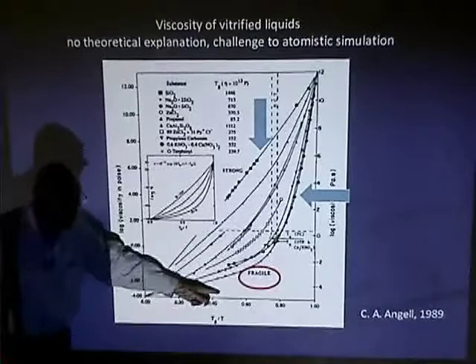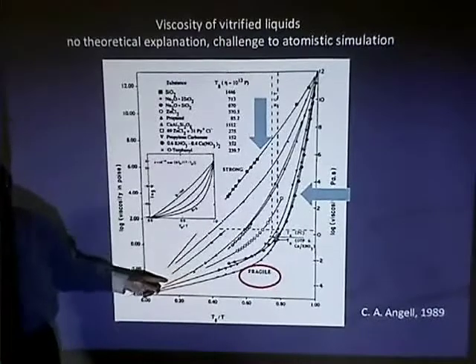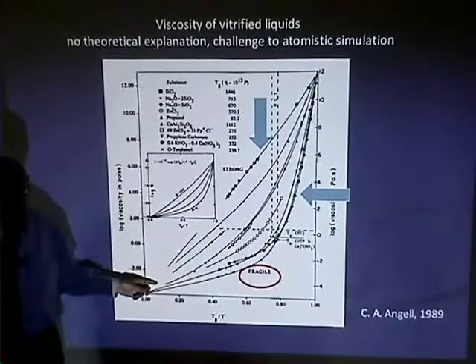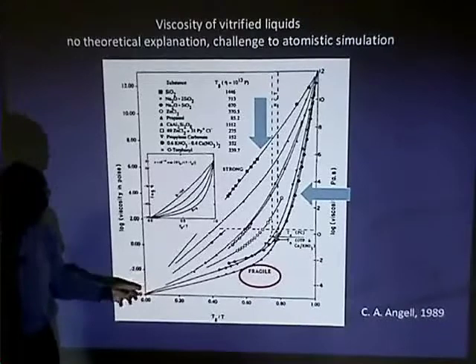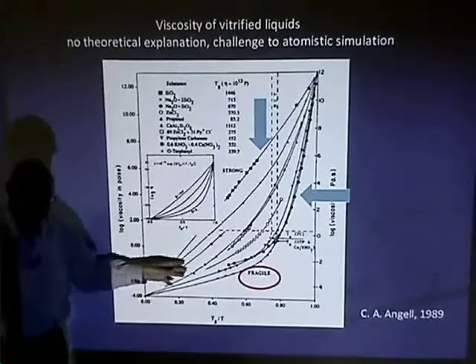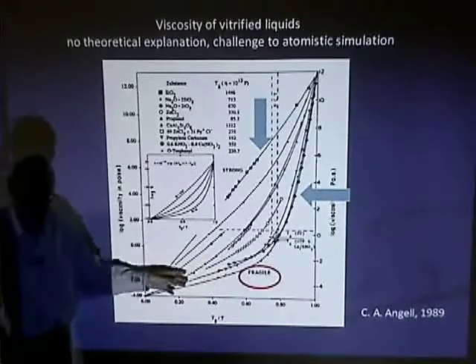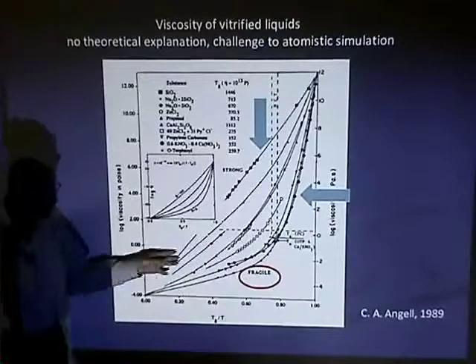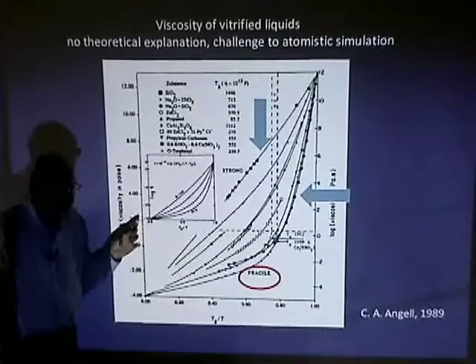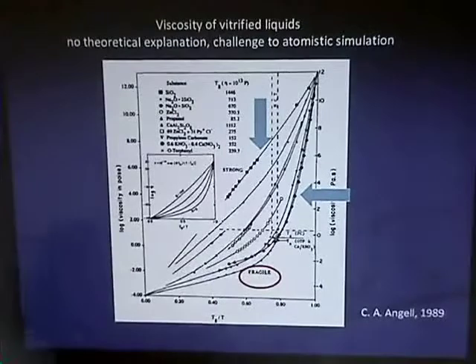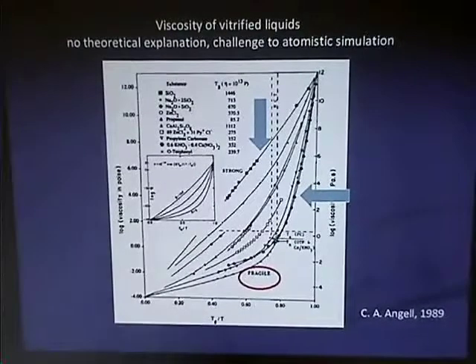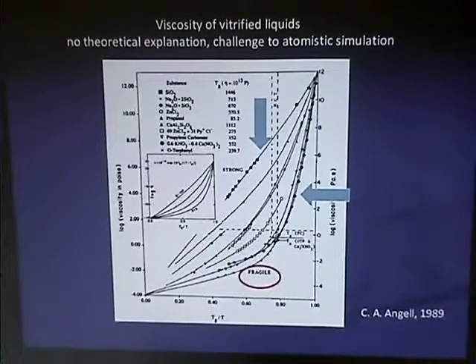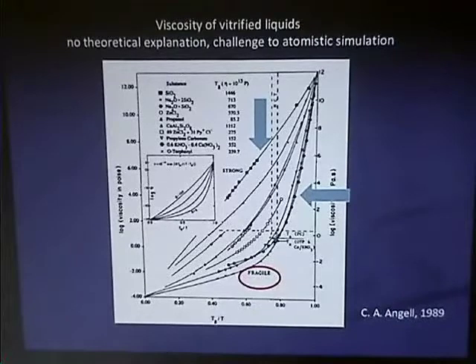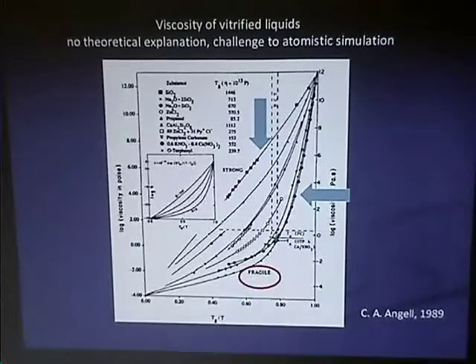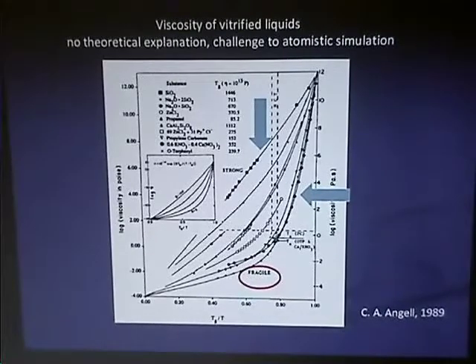This region of high temperature is easy to study because we have Green-Kubo, we can do molecular dynamics, get low viscosity calculations with pretty high accuracy. Once the viscosity gets to be about 10 to the 3 poise or so, that's when the glass blower becomes interested, because that's when the melt is stiff enough to sustain its own weight.